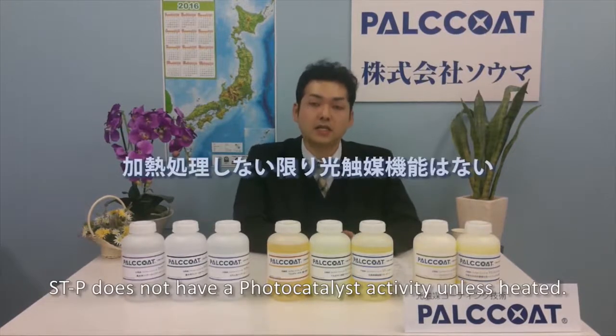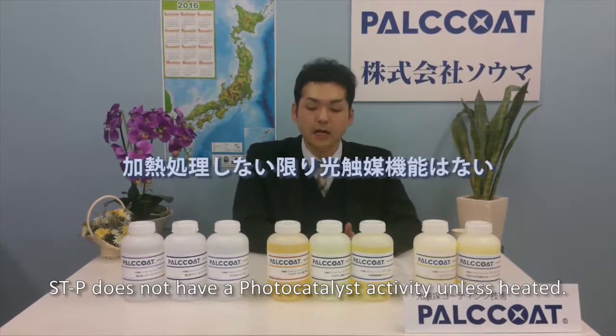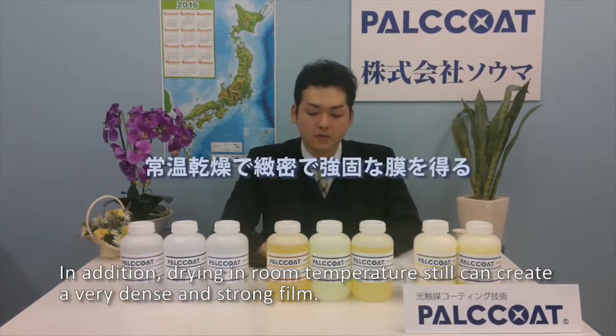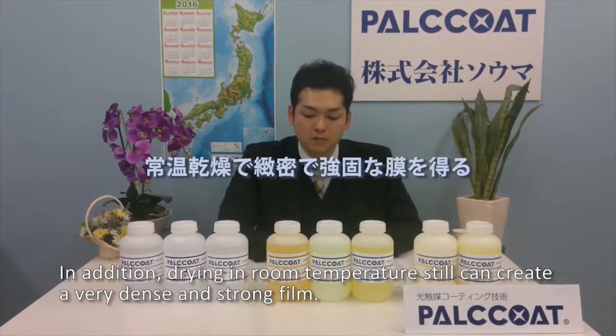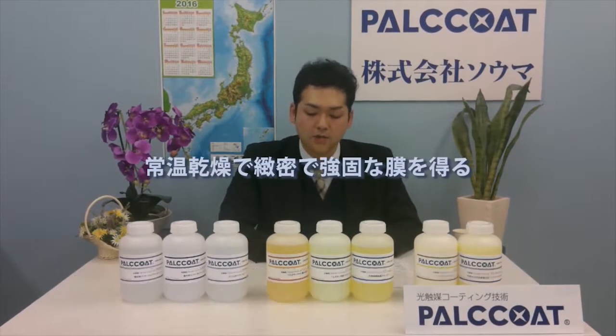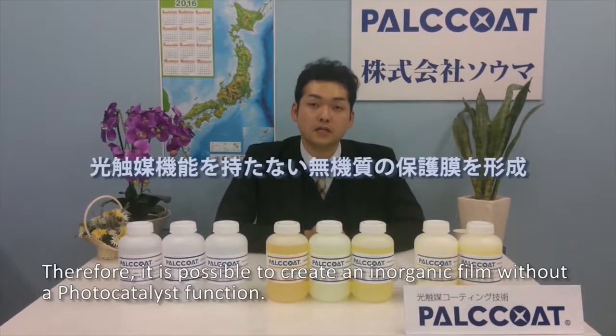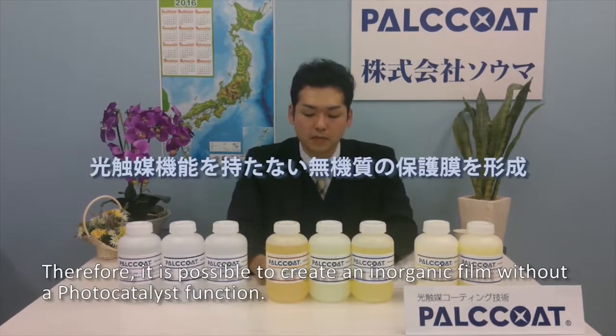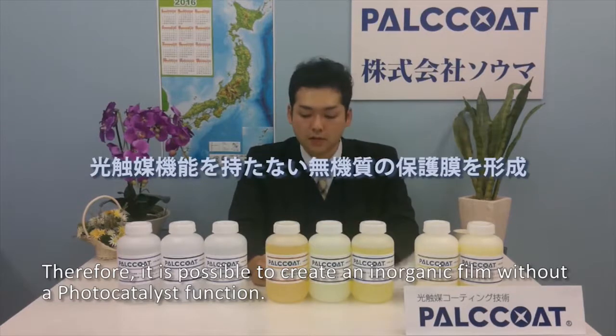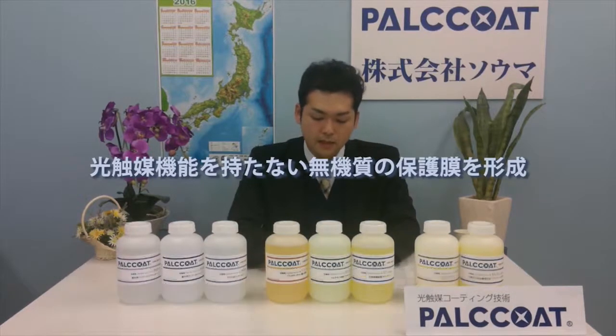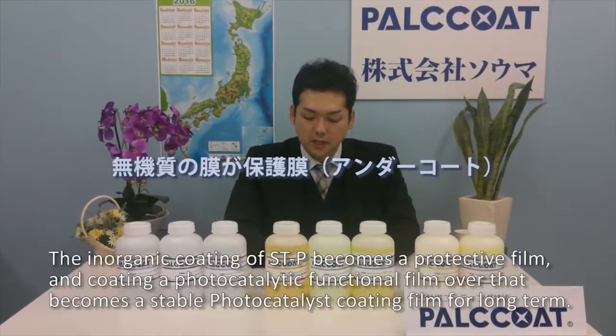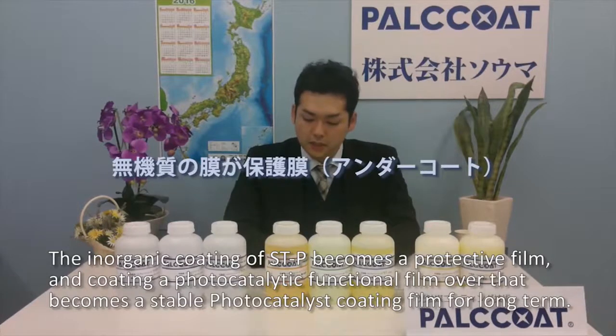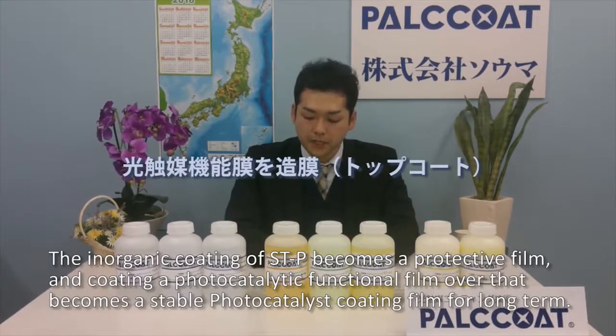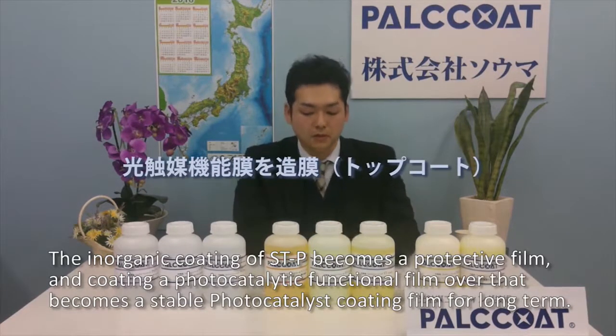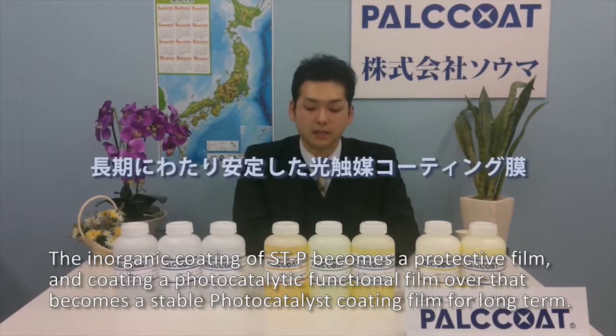STP does not have photocatalyst activity unless heated. In addition, drying at room temperature can still create a very dense and strong film. Therefore, it is possible to create an inorganic film without a photocatalyst function. The inorganic coating of STP becomes a protective film, and coating a photocatalytic functional film over that becomes a stable photocatalyst coating film for the long term.